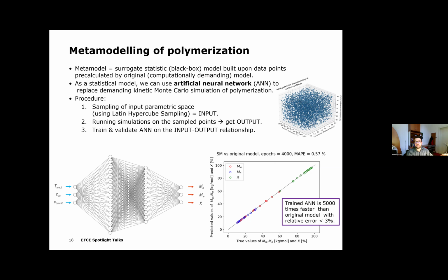There are many different metamodels or metamodeling techniques that are reported in literature. Here, of course, since everybody is working with artificial intelligence today, we had to try ourselves. So we built an artificial neural network with the idea to replace the demanding kinetic Monte Carlo simulation of polymerization. Although so far this model has not been built upon the Monte Carlo polymerization data, and I will explain why. The idea is that we have three input parameters of the kinetic model of PLA production. That is the temperature of the reaction, the concentration of catalyst, and the concentration of co-catalyst.